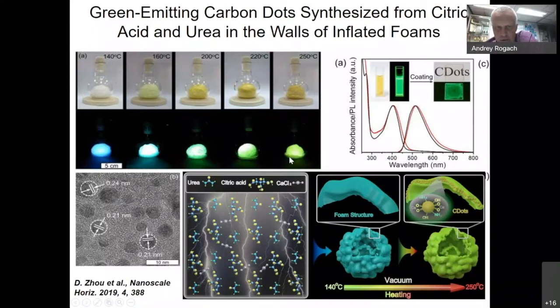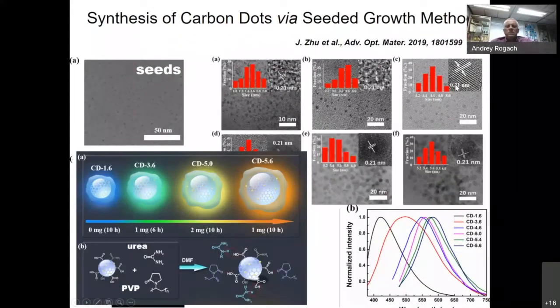And you can also change the color, because at lower temperatures they will be mostly smaller dots or maybe also organic fluorophores. And if we heat them at higher temperatures, they will carbonize completely and deliver us green emitting carbon dots, which we process, we dissolve them in solvents, we make films out of them, and so on.